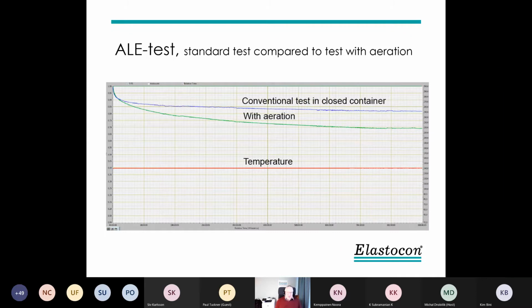But anyway, here is an example of a test we made with a conventional test in a closed container. Normally, when you test rubber in a liquid, you put it in some rubber in a liquid and close the lid. And then the oxygen will disappear quite quick. But in this case, we had applications where we have air present. And then we added the aeration. And you can see we get much more degradation, more relaxation when we have the air introduced. In this case, I think it was an HNBR material tested at 140 Celsius in motor oil. So this has been introduced now in ISO, so we can add that to the aging of rubber in liquids to have an aeration as well.